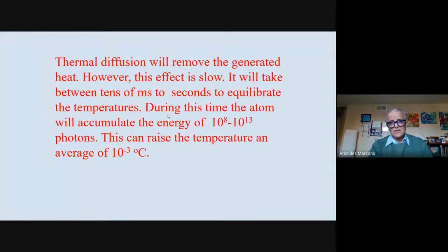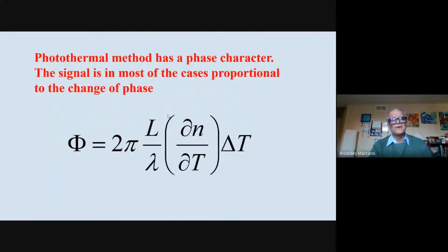So that's a very simple calculation. I recommend you to do it, and that will be cool to show that that is the basic thing for the sensitivity. But there is another point for sensitivity, is that usually what you create in your sample, you generate some changes in the refraction index. And these are phase changes. There are phase changes just because the refraction index changes with the temperature. So here you have this dn/dT, this characteristic. So usually this dn/dT, the gradient of the refraction index, is very small, 10 to the minus 4, and the delta T is 10 to the minus 7, 10 to the minus 3.